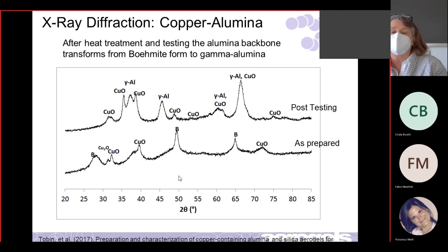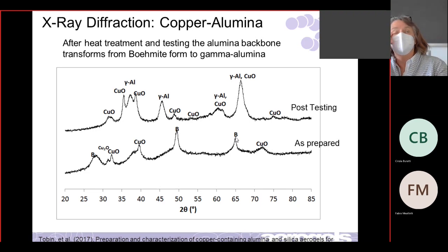So for example, this peak and this peak are signatures of boehmite, which is a form of alumina. So by identifying, and the intensity is important. Boehmite has the highest peak at this angle. You know, the next highest here, the next highest here, and it probably has 4 or 5 more that we can't pick up.